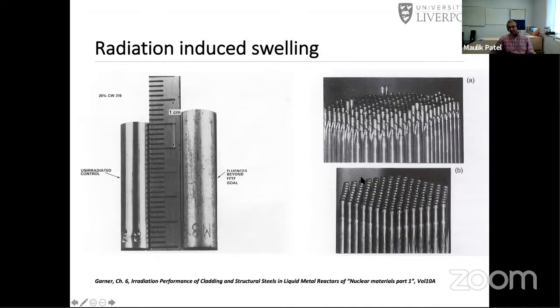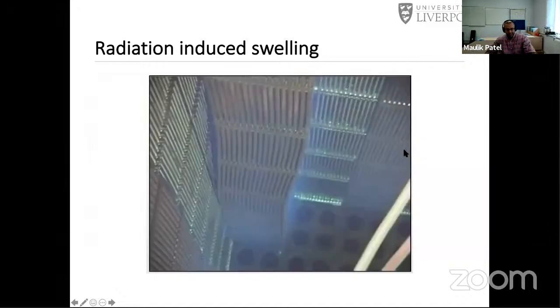Okay, and here is another photograph on the right-hand side where you have a whole fuel bundle with different fuel rods which undergo radiation, and some of them you can see have popped out because they've changed lengths due to radiation-induced swelling. So I hope this demonstrates that atomic scale phenomena can lead to macroscopic scale observations, real change. And because the rods are constrained on two sides, it could lead to buckling of these rods. And obviously then you change your flux profiles.